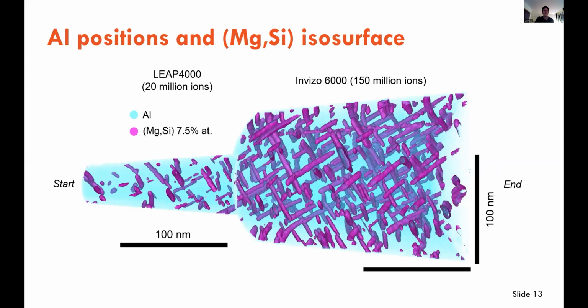So just to quantify it, 35 to 60 nanometers in the LEAP 4000, that's as the voltage increased. Moving it to the 6000 instantly doubles the field of view to 120 and then expands to 160 by the end. The Invizo 6000 has an enormous field of view, and you see a very large number of precipitates very easily.